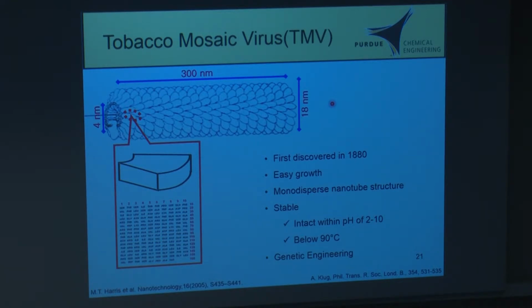Researchers have coated TMV with metals on the exterior surface as well as in the interior surface. The reason why it's such an excellent template is that it was first discovered in 1880, so if it was discovered that length of time ago, you would think we would know a lot about it. It's easy to grow. You can harvest 1 kilogram to perhaps 2 kilograms of purified TMV per acre of land. The particles are very monodisperse, and they form nanotubes, as you can see.